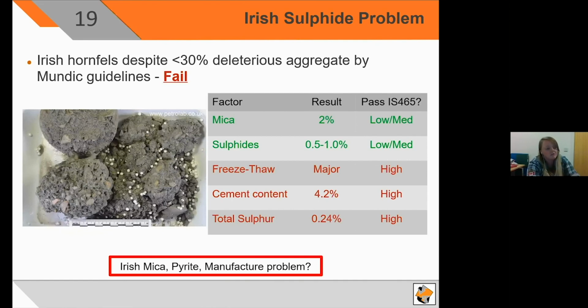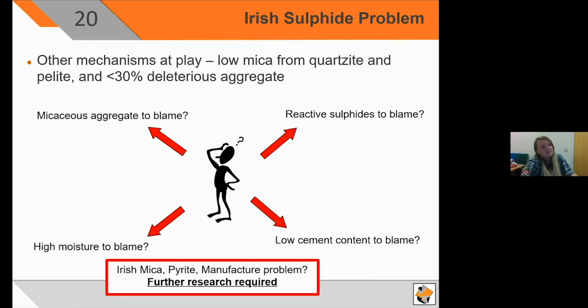However, the total sulfur, 0.24, very high. It's another contradiction. And the cement content is abysmal at 4.2%, and the binder is basically non-existent. So what's actually to blame here? There's low mica from quartzite and pelite. There's less than 30% of deleterious aggregate, which by our Mundic guidelines would pass.